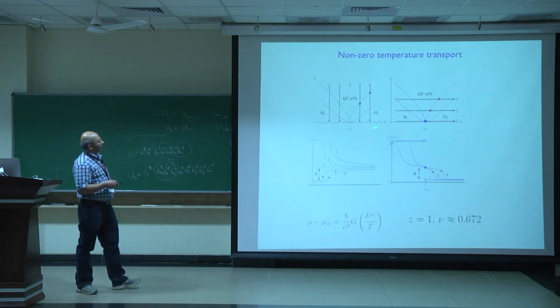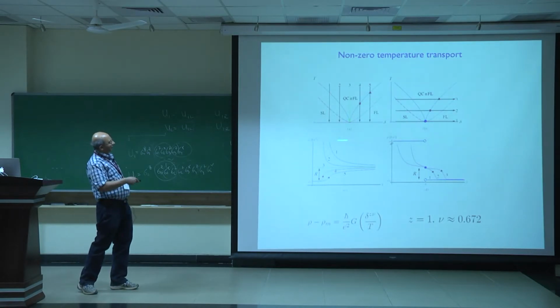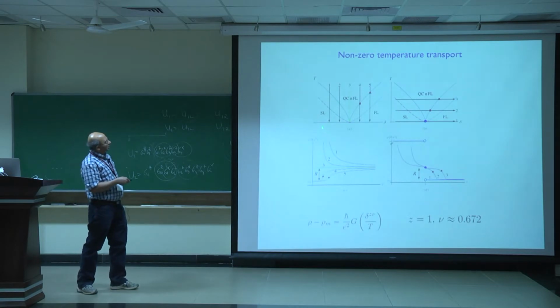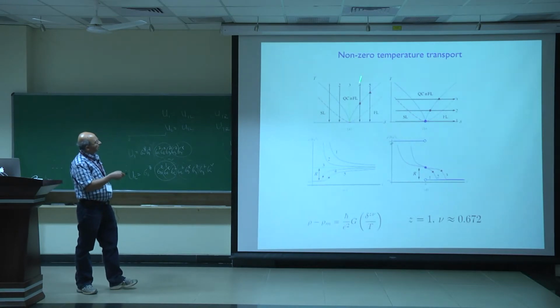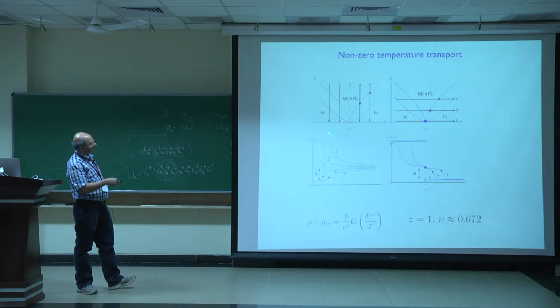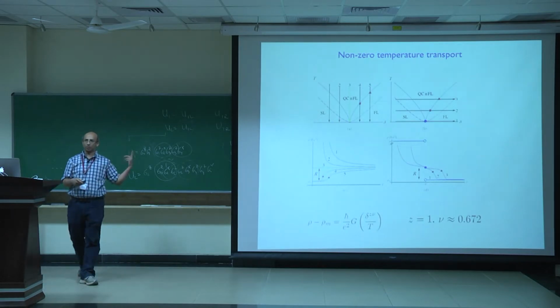So the kind of experiment that one would do is to look at this kind of Mott transition, perhaps in the organics, and take various cuts through this phase diagram at various doping levels, and then plot the resistivity as a function of temperature along each one of these cuts. In the insulator, you should see this insulating resistivity. On the metallic side, you should see a resistivity that flattens out to 0. But then, very close to the transition, this residual resistivity will jump by some number of order h over e squared that we've estimated in this large N calculation.